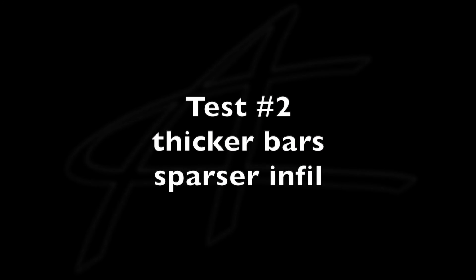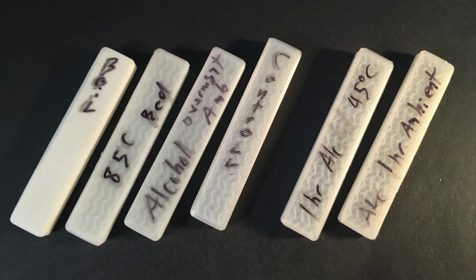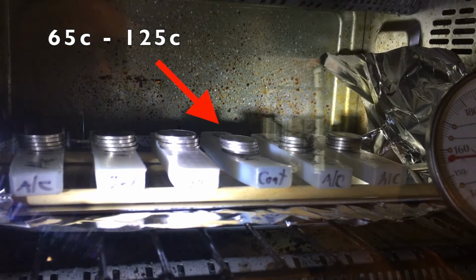Test number 2 was the same deal, but with thicker bars and the sparser infill, so these are much larger bars. And as you can see here, I marked with Sharpie on all of them. We had the boiled, the 85-degree bed. I also added alcohol ambient overnight in a bag. Then we have the control that I added an extra L on the end for luck, I guess. Then 1 hour in the ethanol at 45 degrees Celsius and 1 hour in the ethanol at ambient temperature around 25, 27. And we get pretty much the same result.